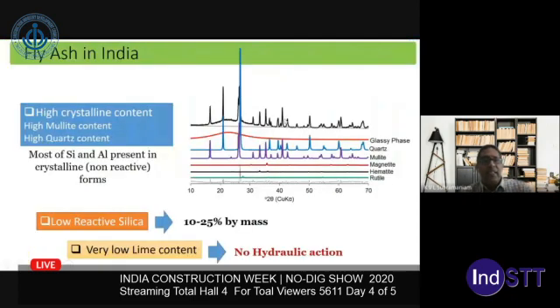So our next step was, through this characterization, we established from XRD based analysis that most of the fly ash is basically oxides, the silica and the alumina locked in crystalline material. If you look at this XRD graph that I'm showing here, a lot of the fly ash is locked in crystalline content of quartz and mullite. Quartz is sand, which is very unreactive. So a large percentage of the fly ash is locked up in these unreactive forms. Basically, the reactive form is this glassy phase, which is shown in this orange line, and that is what we are interested in, but that content is low.